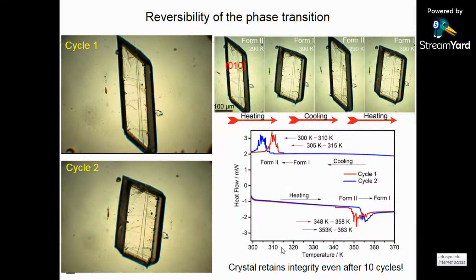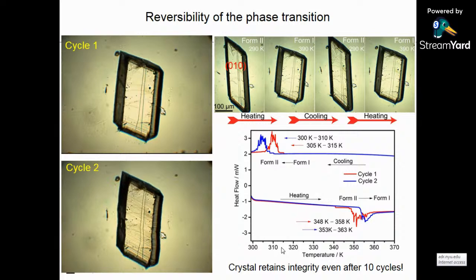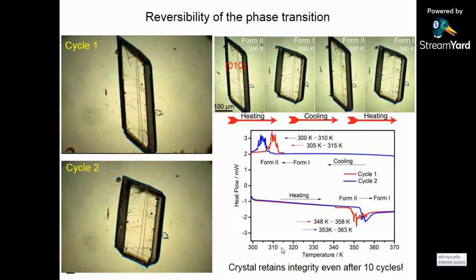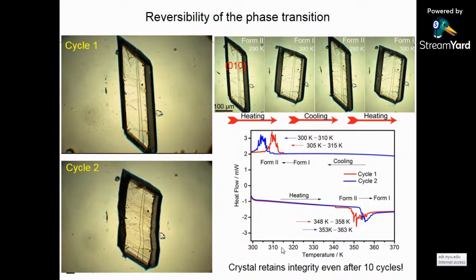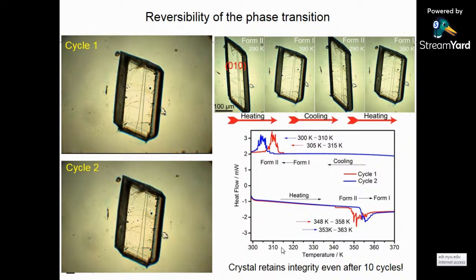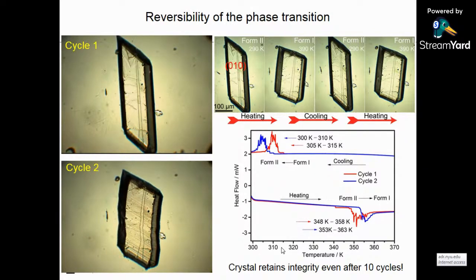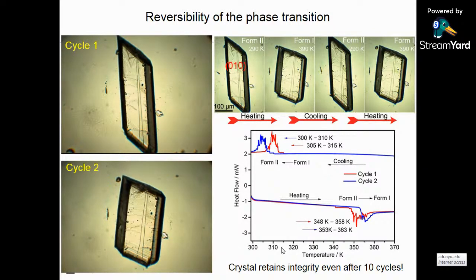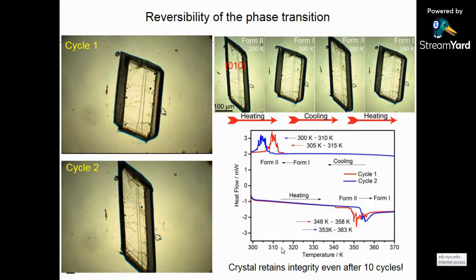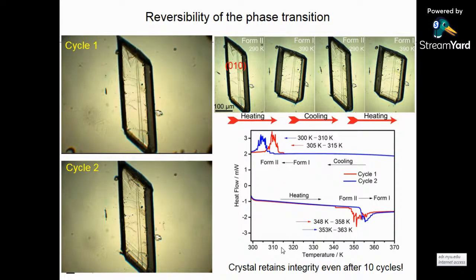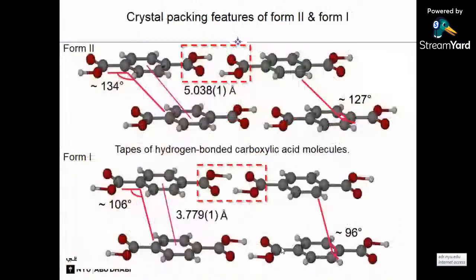This is mainly because of the crystals. When these crystals are placed inside the DSC crucible, they jump, or they transform from one shape to another shape within a time frame. Due to that, you see this kind of sawtooth behavior both while heating and cooling.